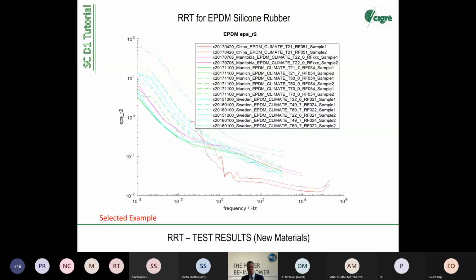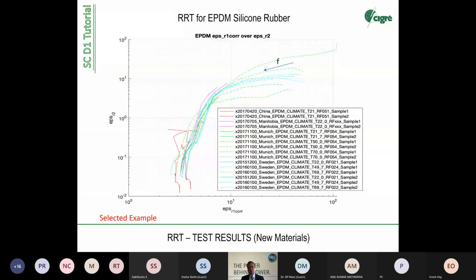So this was not given in this report because the data came at the beginning of September when the report was already finished. But it demonstrated that if we do standardization on equipment, on test configuration, we come all to the same results, more or less. Here also clear signal for Maxwell-Wagner. So you see quarter circle of this phenomenon. Even the results from China, which are out of range, I would say, fit into the curve. I think the parameter was wrong in China, so they measured a different kind of frequency.